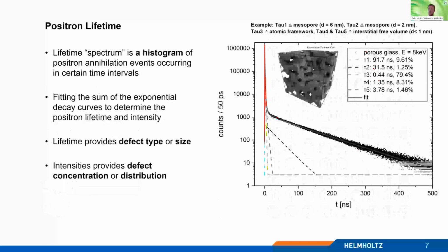So, and at the end, we measure some kind of histogram. This is called a positron annihilation lifetime spectrum, which is more or less a histogram of the time differences we measure. And then they are appropriately sorted. And after that, we fit these decay curves with a sum of exponential decay functions, and we get an intensity and also a lifetime from this. Here, for example, we measured porous glass with 5 positron lifetimes.